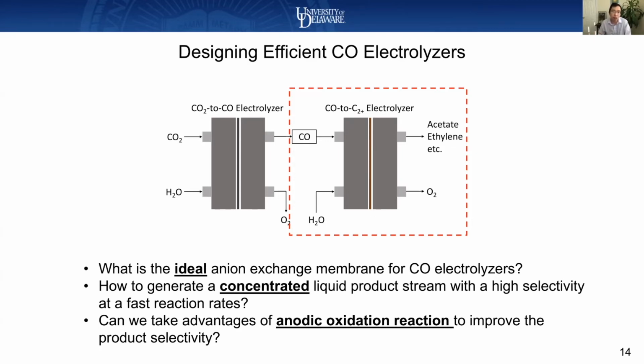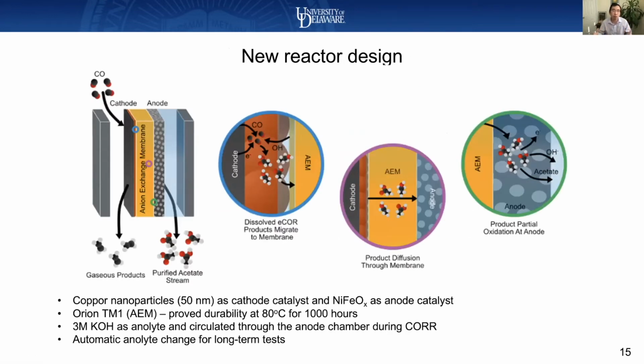This has been ignored, or I never saw any papers mention this, but I want to share this study with you. So some of the new concepts we're trying to bring into this particular work: we first use a very standard catalyst, copper nanoparticles, 50 nanometer, as a cathode material, and we use nickel iron oxide as an anode catalyst. We operate the whole system in a highly alkaline environment, 3 molar KOH. One of the membrane materials we picked is called Orion TM1. It's an anion exchange membrane for fuel cells. This membrane was developed for fuel cells, and they have proved its durability at 80 degrees C for thousands of hours. It seems to work very well for fuel cells. So that's why we're interested in using this particular membrane material for our systems.